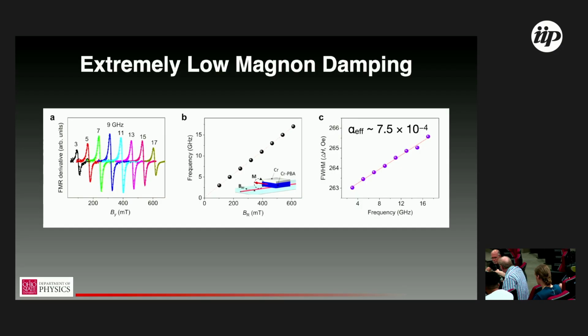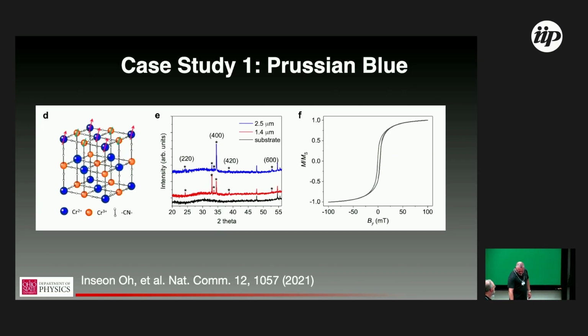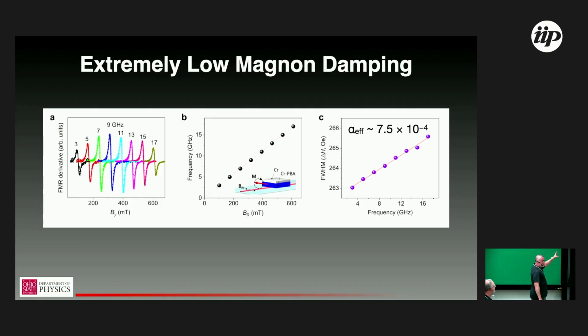Yes, thank you. I had meant to point that out. It's also a nice segue to the second piece. Let's see, is this in here? Well, no, I didn't include that figure. But the way that this is produced is an electrochemical effect. So they essentially put a chromium film into a wet solution and do electrochemistry to build the Prussian blue structure on top of it. So very chemistry forward approach, which is great for materials discovery. And as you can see, it is pointing at some really exciting potential properties here, but is not great at uniformity.